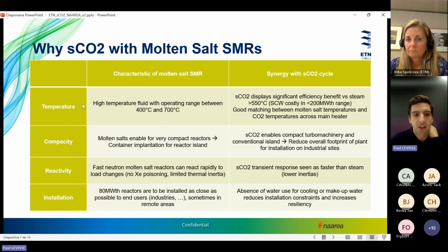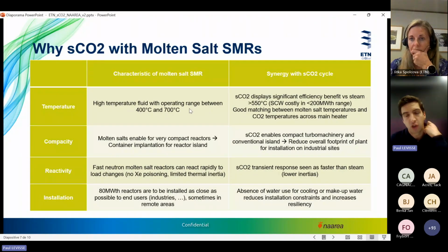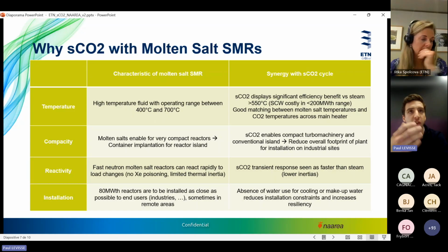The first being temperature. Molten salt is a high temperature fluid because it melts at roughly 400 degrees. So you have to use it above 400 degrees, and it can go up to 700, even potentially higher, but then you get limited by materials. But we've got that operating range between 400 and 700, and well, as Otakar mentioned, sCO2 really starts to have a significant benefit compared to steam above 700, or at least above 550 degrees Celsius.